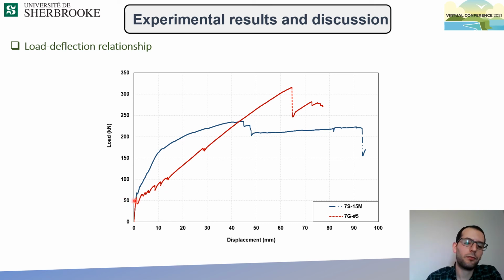The post-cracking stiffness of the ST reinforced specimen was higher than the GFRP reinforced one, which was predictable according to the higher modulus of elasticity of steel bars. But the modulus of elasticity of steel bars was around 4 times higher than the GFRP bars, but the stiffness was only 2.7 times greater. It shows that the GFRP reinforced specimen can also meet the requirements regarding deflection behavior.